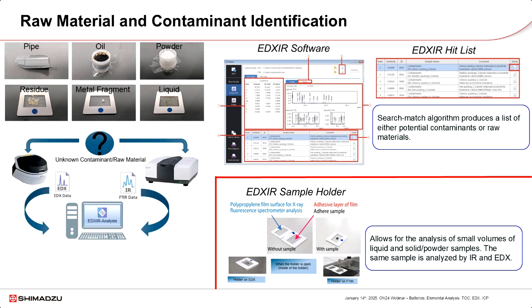Shimadzu has also developed what is known as the EDX-IR sample holder. This sample holder is especially useful for contaminant analysis, since contaminants are often low in volume. The idea behind the sample holder is that you put the sample inside of it and close it like a sandwich. You open it for the IR analysis and close it for the EDX analysis. What's nice is that the same exact sample is being measured by both EDX and IR. In addition, the sample can be easily archived and stored for later use.